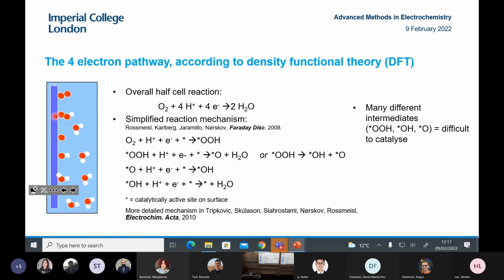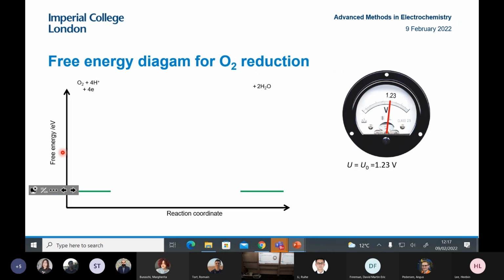And you can start to see what the problem is already when we look at the simplified reaction mechanism. You have many different intermediates in the reaction, and you have to catalyze all these different sub-reactions at the same time. So you're going through OOH, OH to oxygen, oxygen to OH, OH to water. The problem is that they all bind via the oxygen atoms. They all bind in a similar way.